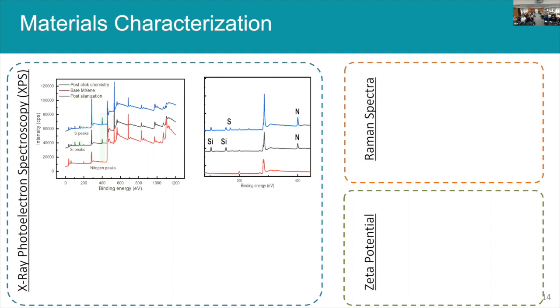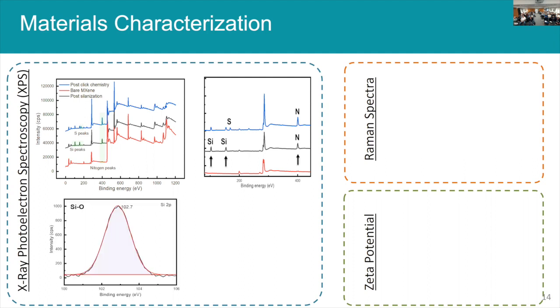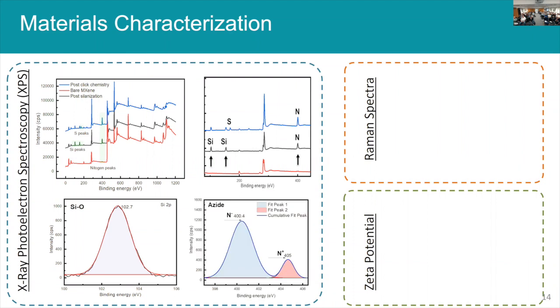And if you zoom in on each of these peaks, as an example of the characterization that we're doing, if you look at the silicon 2p peak, this corresponds exactly to the binding energy of an Si-O bond, which is wonderful. This is exactly what we expect to happen. And then if you zoom in on the nitrogen peak, you'll also see that it is a specific binding energy for the azide group, exactly at 400 electron volts and 405 electron volts. So this is just proving to us, yes, we've got all these functional groups on our surface.